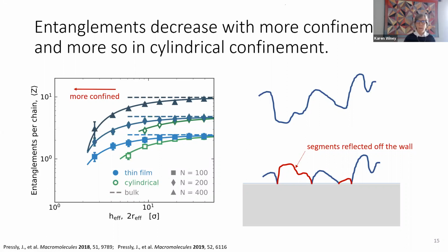The reason there are fewer entanglements is really because of the idea that the random walk has to reflect off an impermeable wall. So if this is our polymer chain taking its random walk, and then we insert a wall there, the random walk is reflected back into the polymer melt. And because these red segments are in the polymer melt instead of inside the wall, they displace other polymers, and so there are fewer entanglements with other chains. There are actually equations that people have developed to explain this quantitatively. So this is a nice comparison between the cylinders and the thin films: fewer entanglements with further confinement, and this drop-off is more dramatic at higher molecular weights.